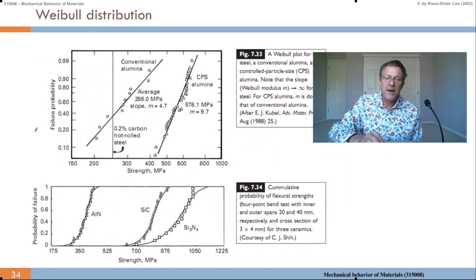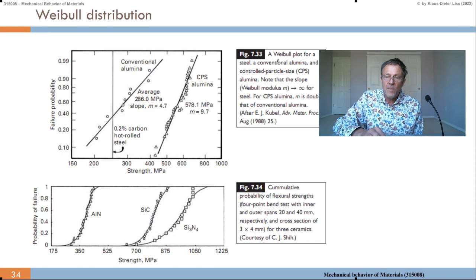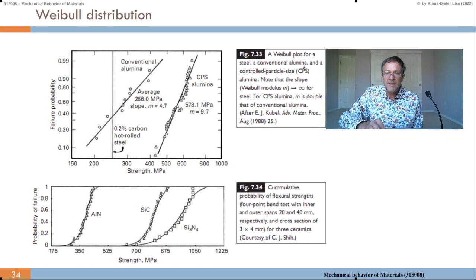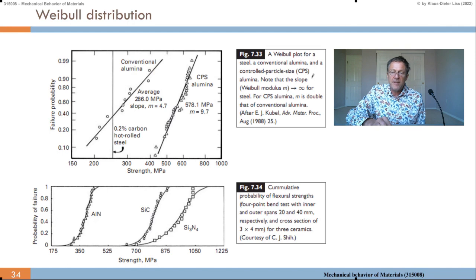Here are some examples on the Weibull distribution. So there's a Weibull plot for steel, a conventional alumina, and a controlled particle size alumina. Note that the slope, which is the Weibull modulus, goes towards infinity for steel. So steel is here, 0.2 carbon rolled steel. For the controlled particle dispersed alumina, the M is double that of the conventional alumina. So for the conventional alumina, we have a relatively low slope, and the slope becomes steeper for the controlled particle size. That means all the particles have the same size.